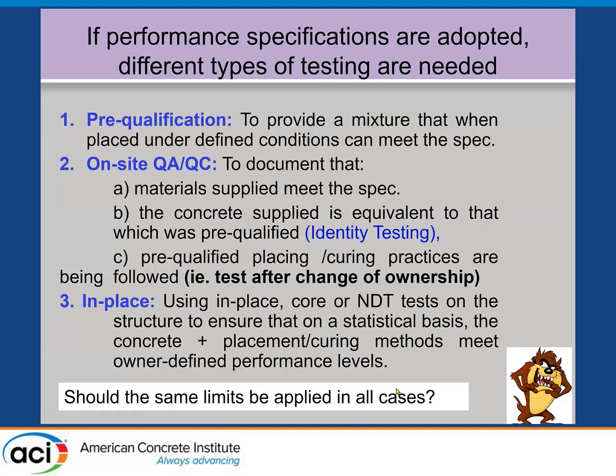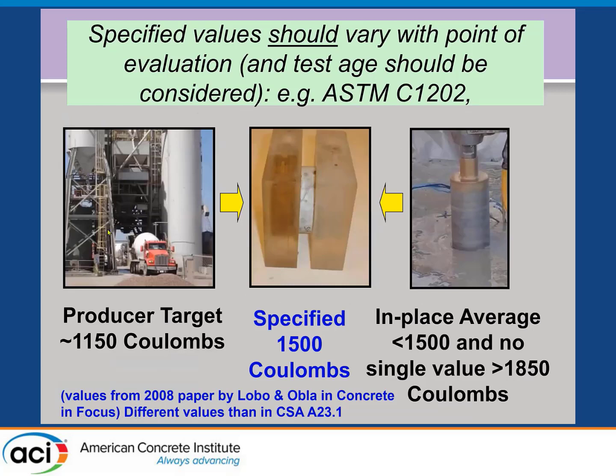And one question that comes up is, should we use the same acceptance limits in all cases? An example of that, and I took some data from a paper that Karthik Obla and Colin Lobo wrote some years ago. This is what they would do. If you spec 1500 coulombs in 1202, then the producer, to be confident they're going to meet that on arrival, needs to target something lower. And if you're going to test in place, you've got to say, well, look, we need some value for acceptance, which could be 1500. But then they have said, because of the variability, they would go up to 1850 for a single value. It differs from what we adopted in CSA, but it's in the same range. So you allow for single values that exceed that as long as the average stays below the spec value.